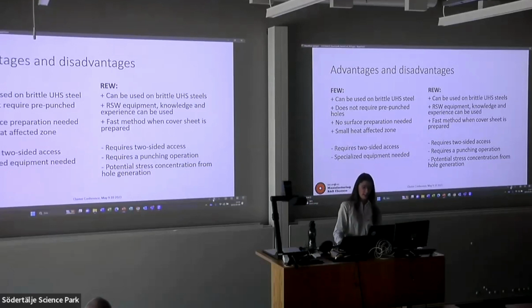For resistance element welding, a large positive aspect is, of course, that you can use your standardized spot welding equipment that is already in place in many manufacturing plants. You can also apply your knowledge and experience from spot welding onto this process. It is a fast method once the cover sheet is prepared with the resistance element. Also in this case, you need 2-sided access, of course, the punching operation, and then you can get some potential stress concentration from the hole generation.